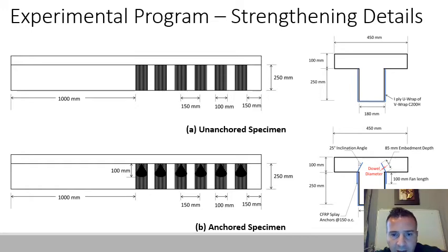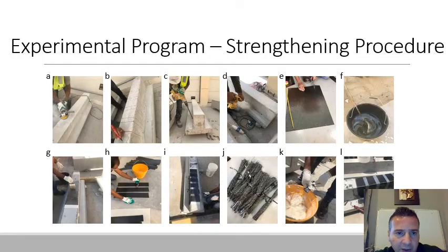It's very interesting, and the procedure for strengthening is easy. You just drill a hole, and then you punch in the anchors with epoxy until you have a strengthened structure. Let me show you the preparation of the specimens. These are the control beam specimens cast in ready mix concrete. This is the preparation of the U-wraps, and you can see them here around. And these are splay anchors, which were fabricated manually by the labor and the student. Then you put the epoxy, put it inside the hole, and you have a very nice structure presented here.